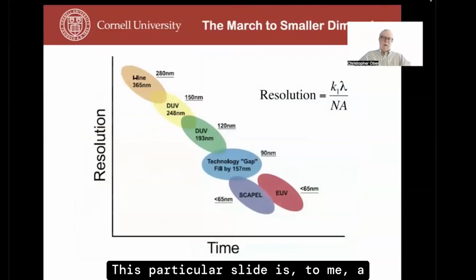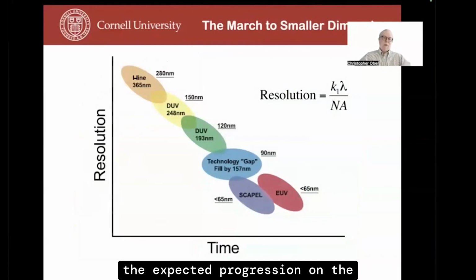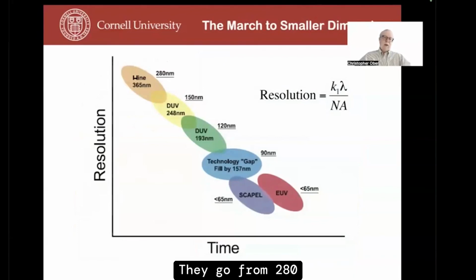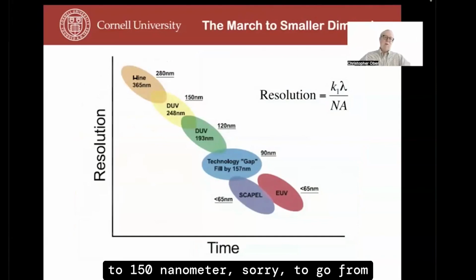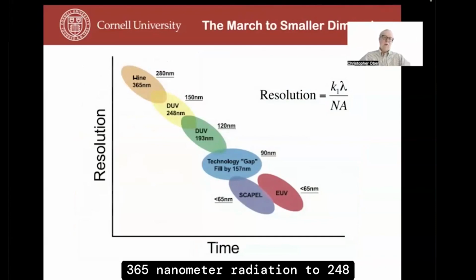This particular slide is, to me, a very interesting historical document, because again, it shows the expected progression on the ITRS roadmap to go from 280 to 150 nanometer, to go from 365 nanometer radiation to 248 nanometer radiation to 193 nanometer radiation. And then around the year 2000, it was thought that 157 nanometer lithography would step in for a short period of time, provide a technology gap fill, and then it would either be SCAPEL projection, e-beam lithography, or extreme ultraviolet lithography. Nobody knew for sure at that time. And history went in a somewhat different path.